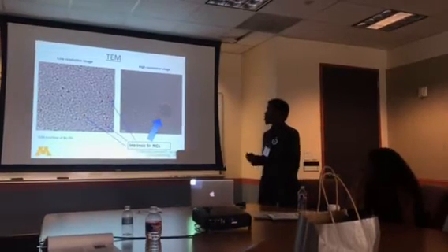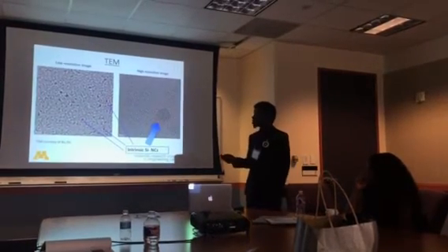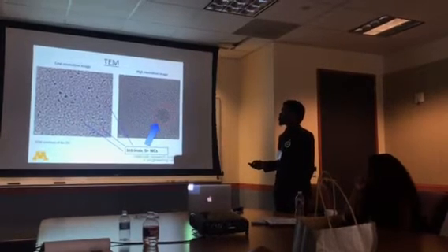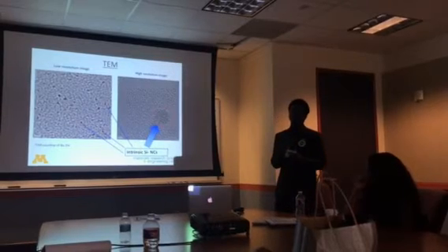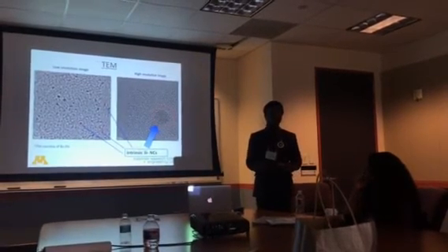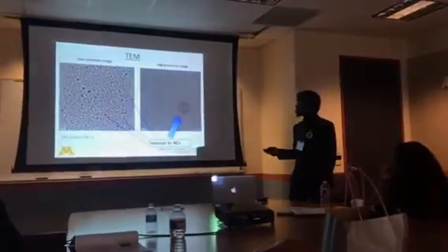So this TEM characterization technique was provided to me by the courtesy of my graduate mentor at the University of Minnesota. And as you notice here, in this low resolution image, there's an agglomeration that happened because the doped silicon nanocrystals were placed into a solution of water, and the lack of solubility of our doped silicon nanocrystals caused this agglomeration, aggregation, sorry.